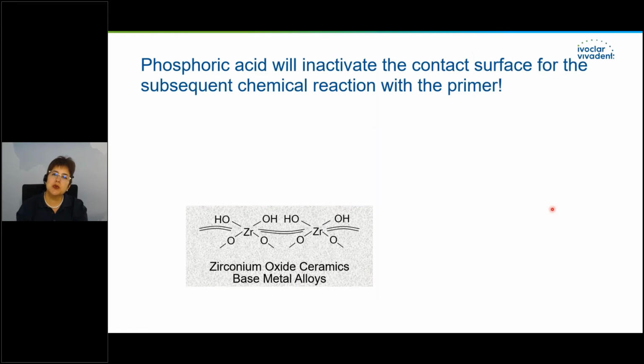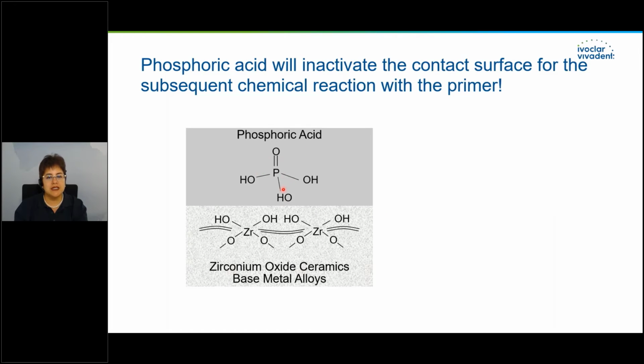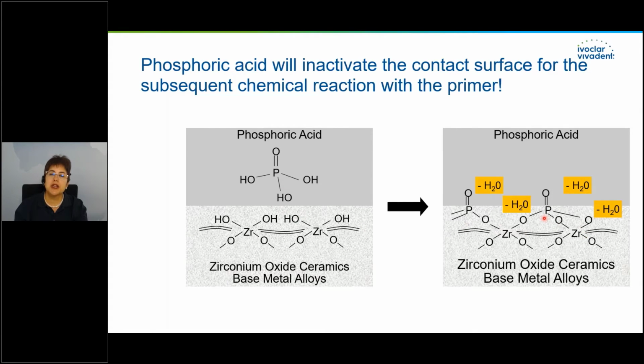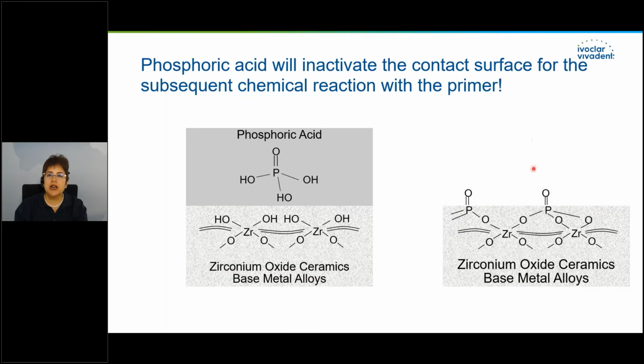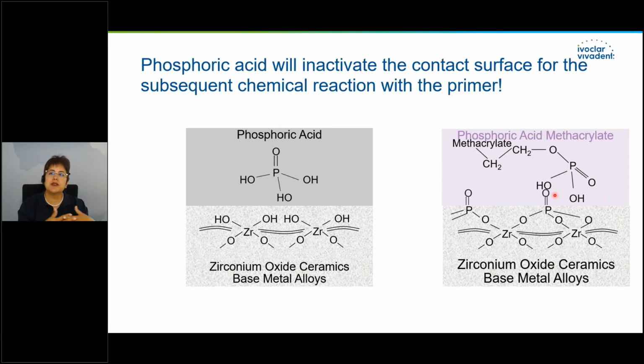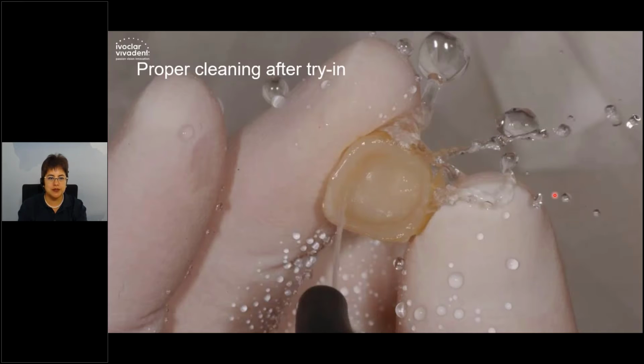But what happens if I use phosphoric acid as a cleaning agent? Phosphoric acid also has OHs, and they will react and create a bond and liberate water. So after rinsing this away, if I want to come with my MDP, there will not be a possibility for reaction. Therefore, the chemical bond decreases so dramatically. So do not always use the same protocol for glass ceramic and for zirconia. You have to think about which materials you are using, and then we have two different protocols.